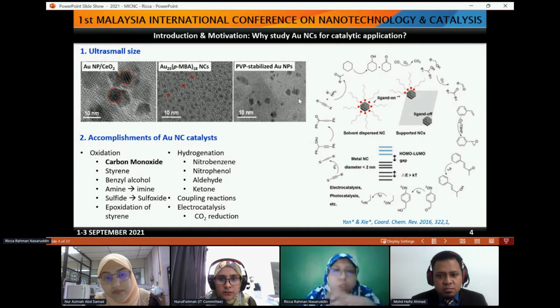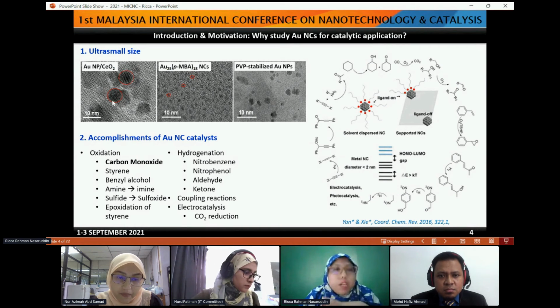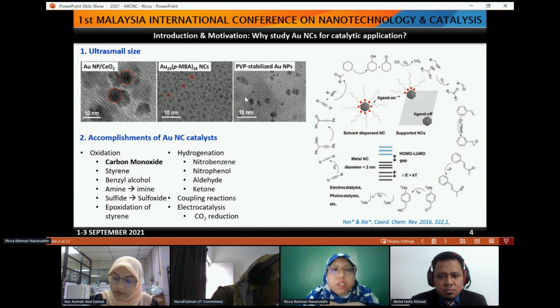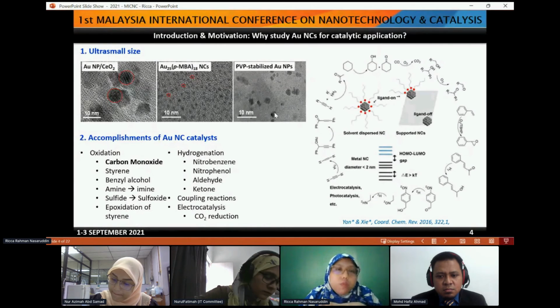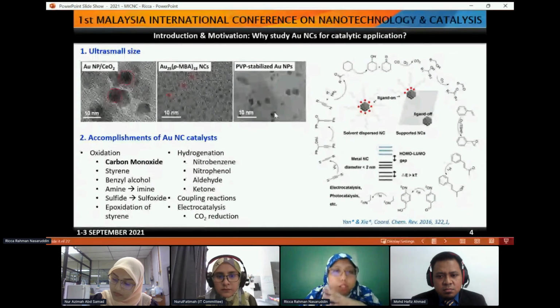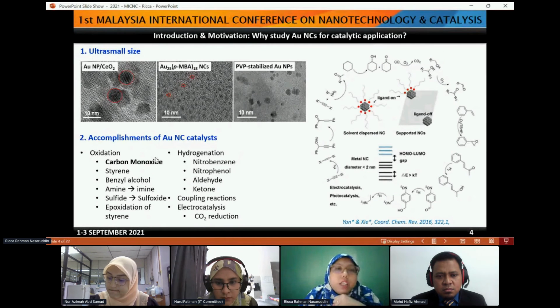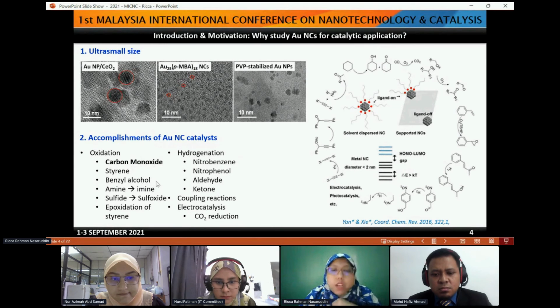And this is the common gold nanoparticle. If you look carefully at the differences between particle and cluster, this one has high monodispersity, but this one has different sizes. If you stabilize it using polyvinylpyrrolidone, you can have different sizes. So to get a better monodispersion, you need atomic precision, and then you can have better monodispersion.